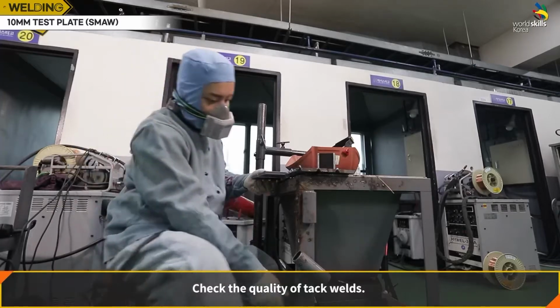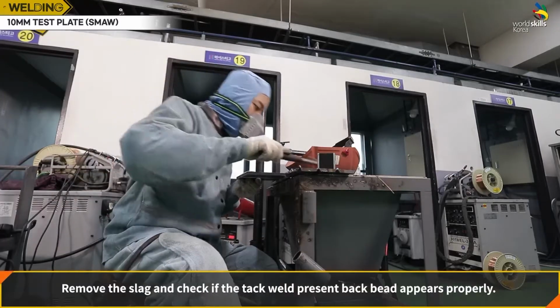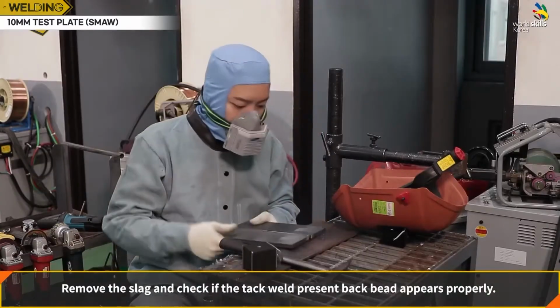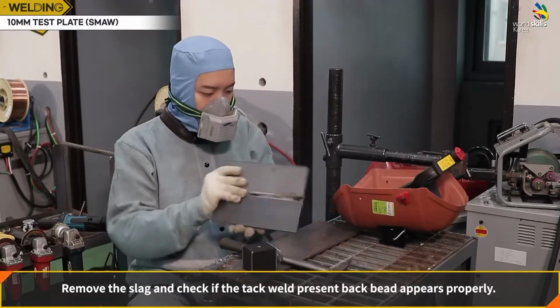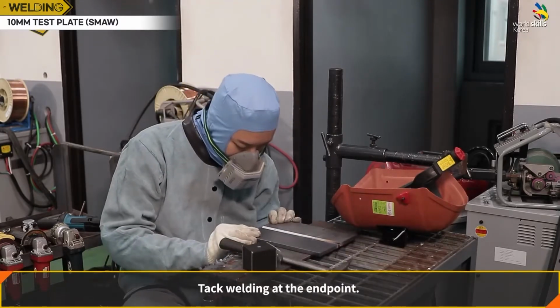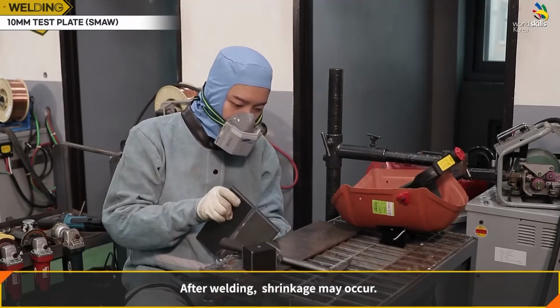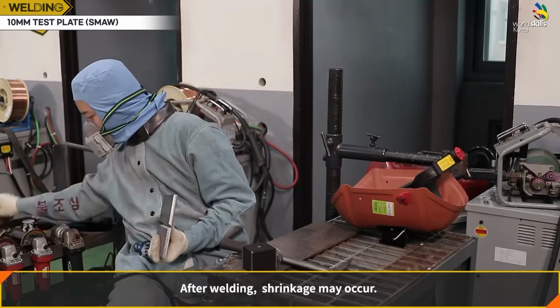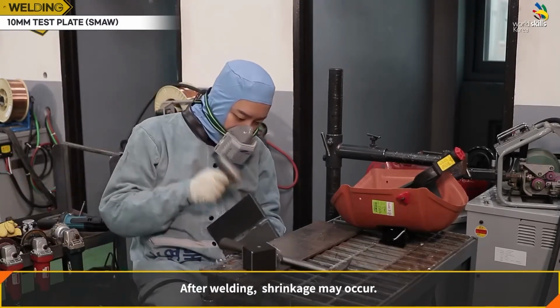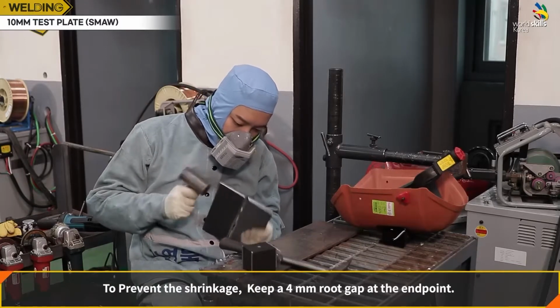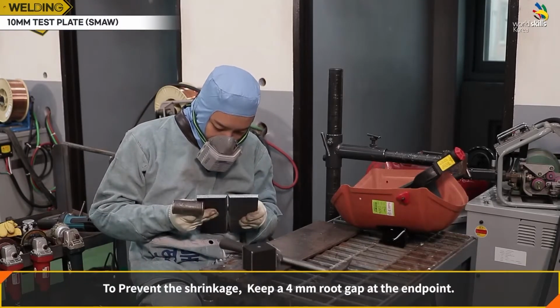Check the quality of tack welds. Remove the slag and check if the tack weld presents the back bead properly. Tack welding at the endpoint. After welding, shrinkage may occur. To prevent the shrinkage, keep a 4 mm root gap at the endpoint.